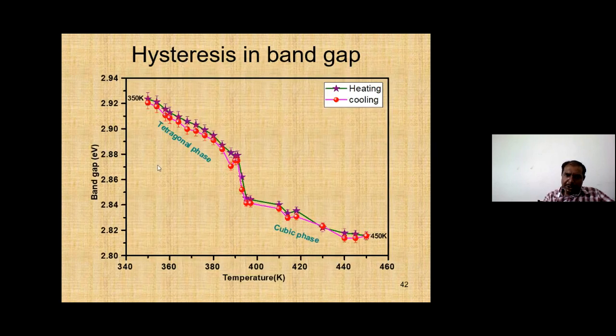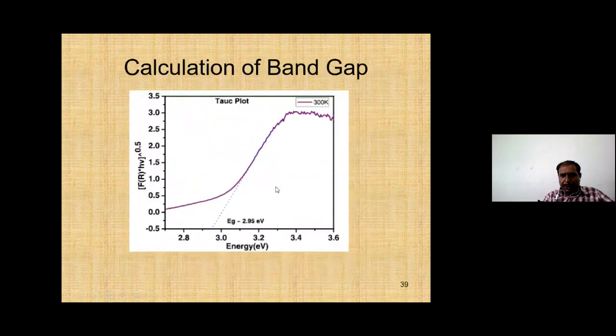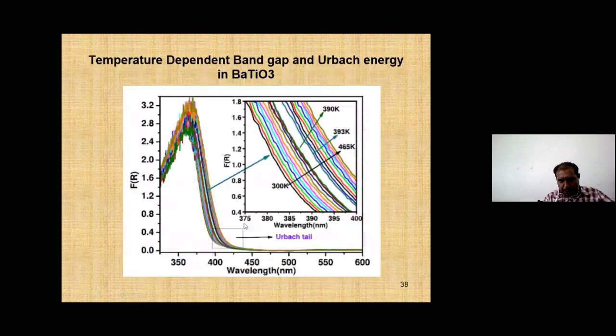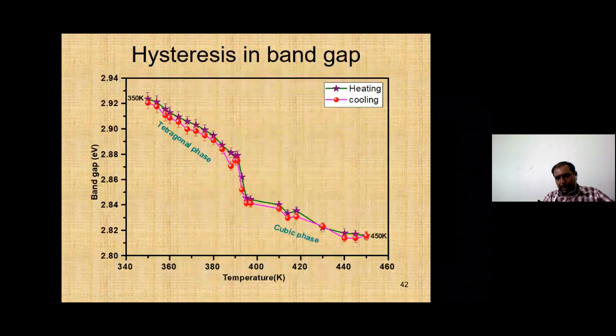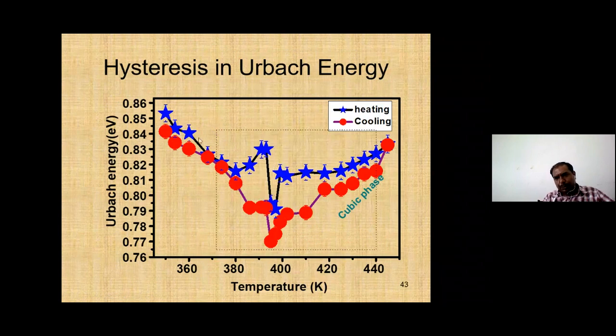In fact, we have measured this hysteresis in the value of band gap in the heating and the cooling cycle, and you can see that the hysteresis is really very small when you measure the band gap as a function of temperature. Since we had the complete optical absorption data, we have the value of band gap and we also have the value of Urbach energy. So along with the band gap, we have also plotted the Urbach energy as a function of temperature in heating and cooling cycle both. And this is the result. When we plot the Urbach energy, or the electronic disorder, in heating and cooling cycle, we observe that there is a significant amount of hysteresis present in the sample. This was really a very surprising result for us.